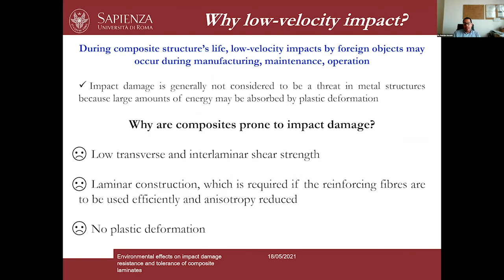Okay, so the next step is to understand why a low velocity impact can be a serious threat to composite materials. First of all, because these kinds of events can occur in the everyday life of a composite material: during manufacturing, during maintenance, during operation. And the biggest difference of composite materials compared to metal structures is that metal structures can usually absorb a large amount of energy by plastic deformation. But when we deal with composite materials, there is no plastic deformation, or at least it is very, very limited compared to the plastic deformation of metals. And in addition to this, composite materials usually show a pretty low transverse and interlaminar shear strength. And another problem is related to their laminar construction.